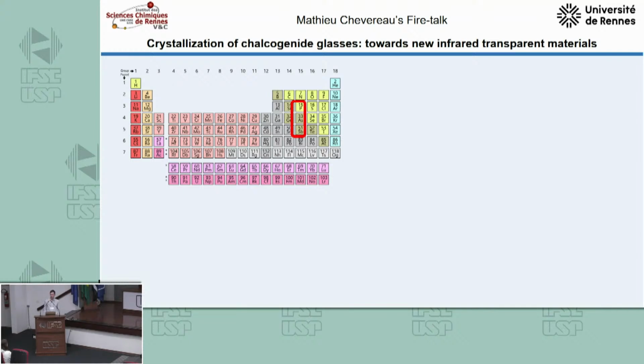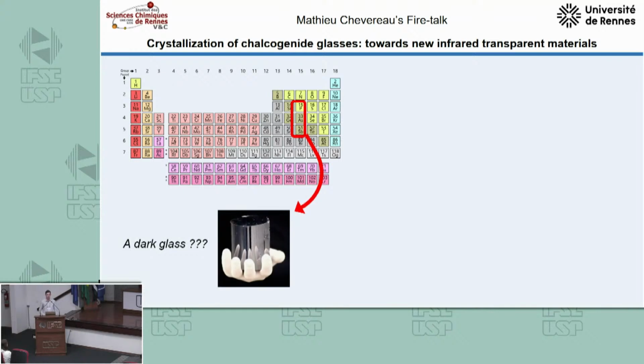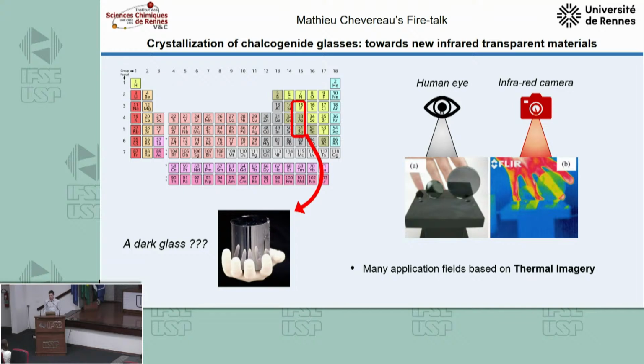So we consider non-oxide glasses. By using these elements, we do not make visibly transparent glasses. We make, as you can see, dark glasses. So they are useful for infrared transparency. As you can see, they are transparent in the near and medium infrared region, which is very useful for plenty of applications in thermal imagery.